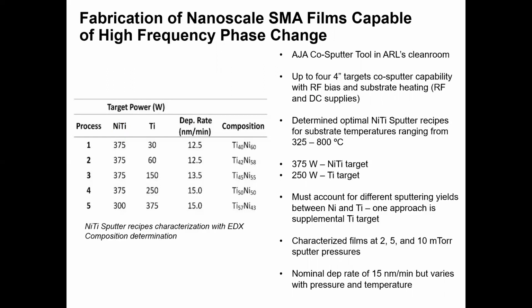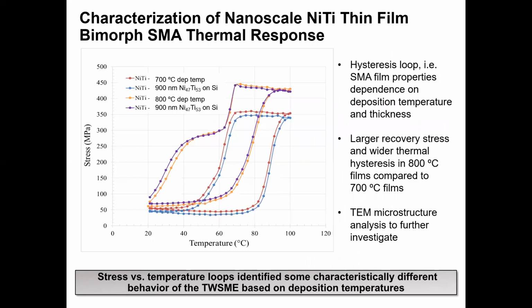A nominal deposition rate of 15 nanometers per minute was determined from using this process. And from there, I investigated a wide variety of sputtering pressures ranging from 2 to 10 millitorr, and substrate temperatures ranging from 325 degrees to 800 degrees. And then finally, this SEM equipped with EDAX was used to verify the film composition, generally to within 1 or 2 atomic percent.